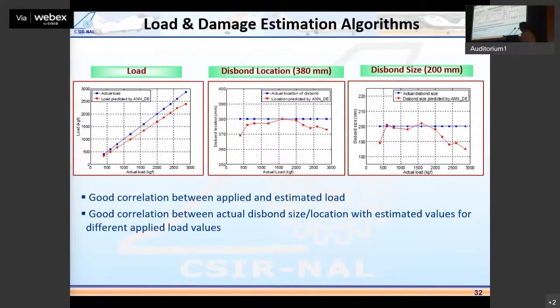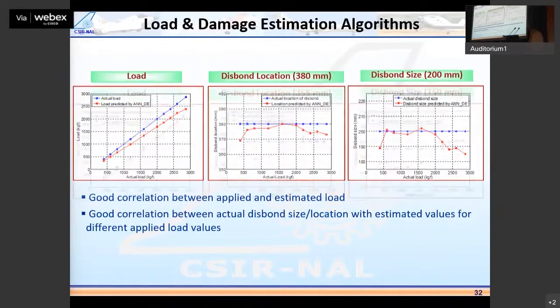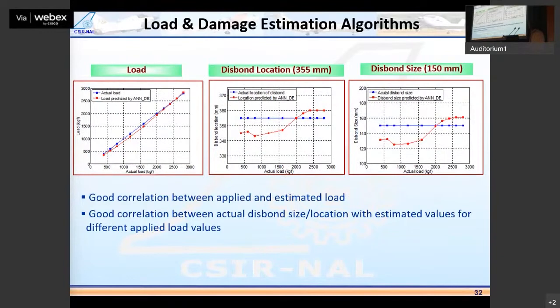And the results here, we look at, first of all, location. It is very important to first get the location right. We have done a number of algorithms, triangulation, scan-based, to get the location. You can see the debond is located at 380 mm. And also, this is a function of loading. When the aircraft is flying, it is loaded at different times, at different levels. Can I find it out at all the different loadings? So you can see here, I've loaded only 500 kgs, and here it's 3000 kgs, and you can see very close correlation to the location. Similarly, the damage size is 200 mm, and you're pretty accurately able to predict the damage size. This is again for another case where the debond location is at 355, and the bond size was 150.